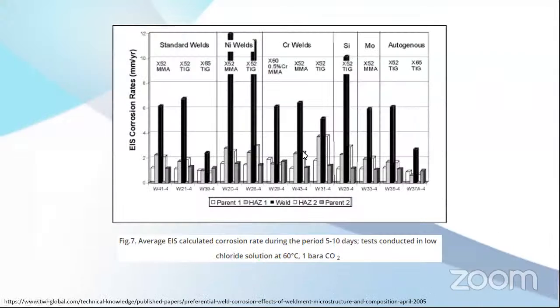And this is the testing that was done by TWI. So they're testing, if using consumables with different chemical composition, what is the effect? You can see the weld is the black one, and the rest is the parent, and beside this are the heat affected zones. As you can see, the result is inconsistent. Sometimes even with matching consumables, you can have higher corrosion in the welds, and sometimes you don't. And in the nickel addition welds, 1% nickel, you get very high weldment corrosion.